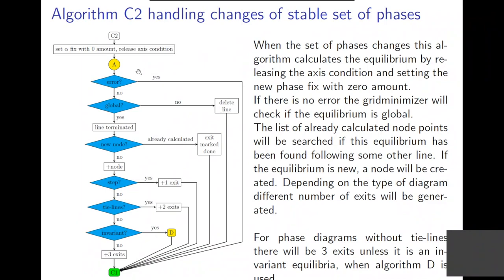So how does the algorithm work when you change phases? When you have a phase change, you change your conditions, you set that a new phase should be fixed and release the remaining axis condition, and you calculate the equilibrium. If that doesn't work, you go back and give up this line. Then you check again that this equilibrium is actually a global equilibrium, that you haven't walked into a miscibility gap or something like that. And then if you have done that, you delete the line because it goes into a metastable region. Otherwise, if it is a global equilibrium, then the line is terminated and you should create new lines starting from the node point.